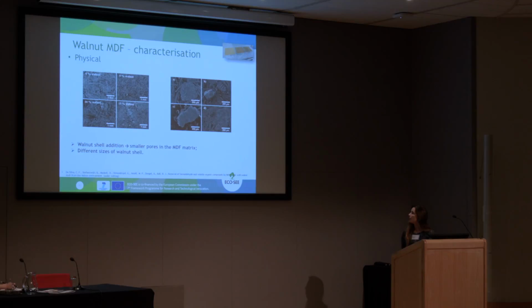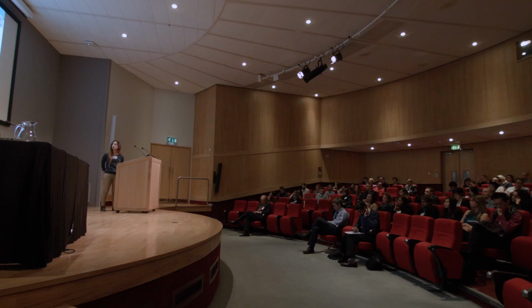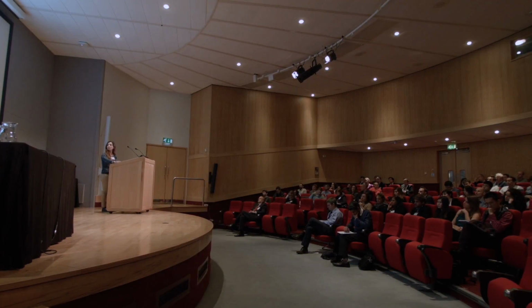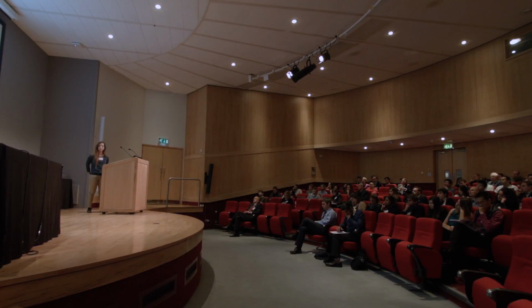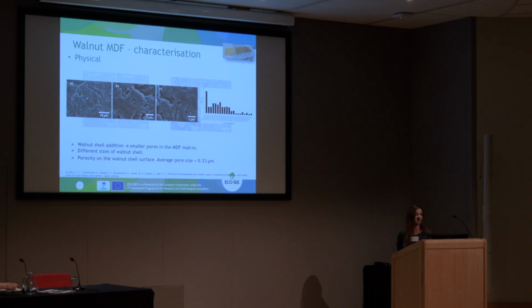Trying to explain why this happens, well, by increasing the amount of walnut, we are changing the microstructure of the material. So we are increasing the surface area. And also, I went a bit further, and the walnut shell surface is very porous. So that's why these materials are absorbing formaldehyde and VOCs.